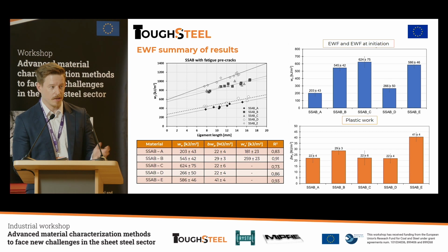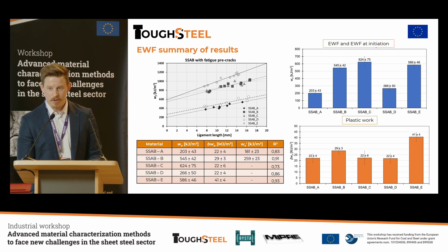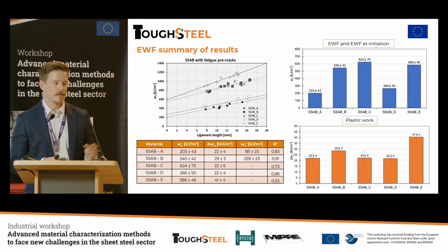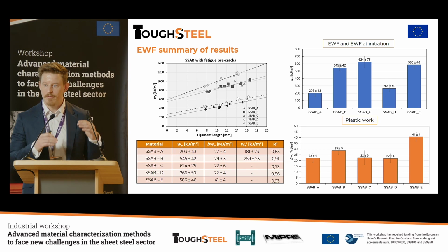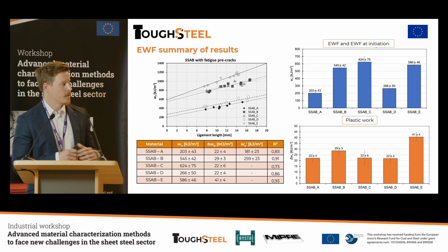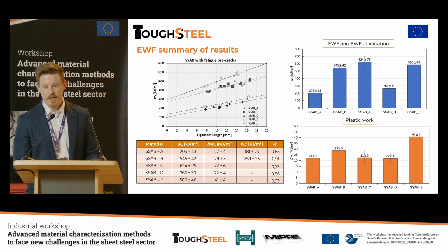Some results from the essential work of fracture. If you have more questions related to this, I think Laura can help. The thing here is that if we look at the essential work of fracture values, again, we have two different levels. Let's say the low level is around 200, and the high level is above 500, even 600. So really distinctive differences between these materials.